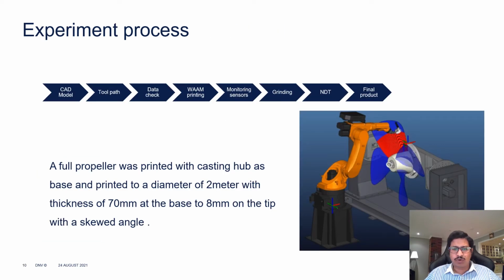For this experimental process, we want to make a full propeller, which is to be printed on a casting hub. It was printed to 2 meters with a thickness of 70 millimeters at the base, and it slowly converged to 8 millimeters at the tip.